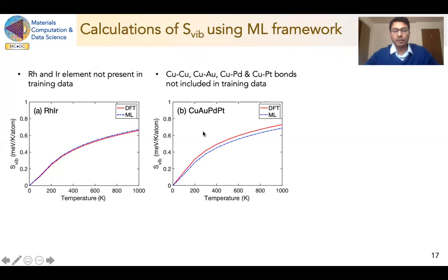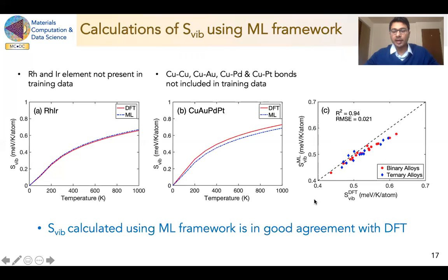Another example of copper, gold, palladium, platinum, equiatomic alloy. Here also you can see that there is a good agreement between the framework predicted vibration entropy and DFT across the temperature. And here we did not include copper-based bonds into the training data. Similarly, we have calculated vibration entropy using a framework for various binary and ternary alloys at 500 Kelvin. And here also you can see that there's a good agreement between DFT and ML with R square 0.94 and RMSE 0.021. So overall, our model is able to calculate the vibration entropy for FCC alloys, irrespective of the composition or number of elements.